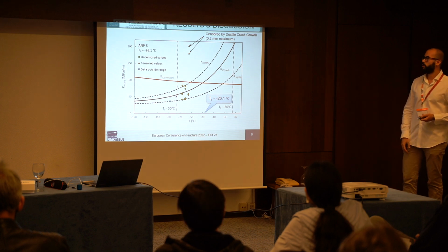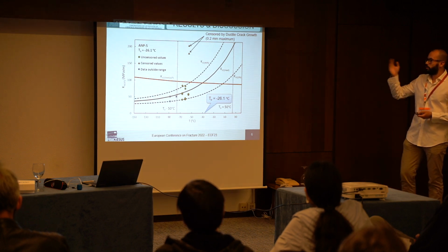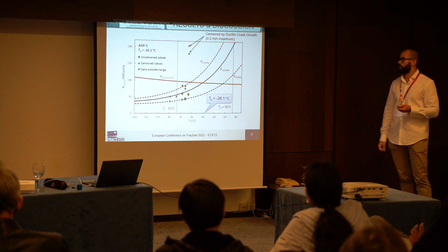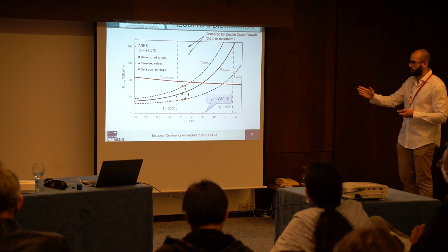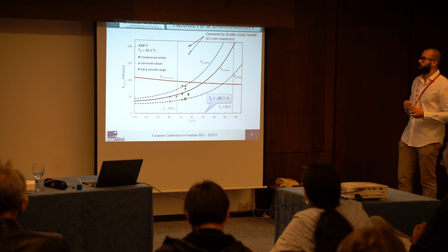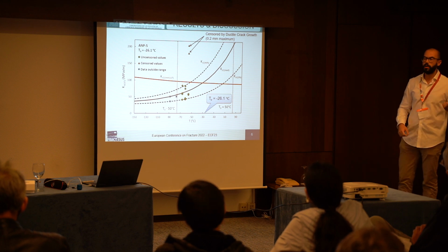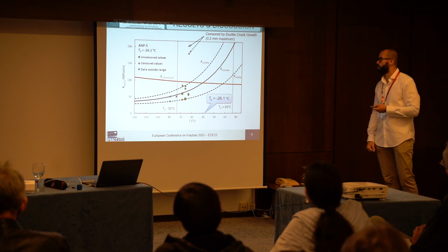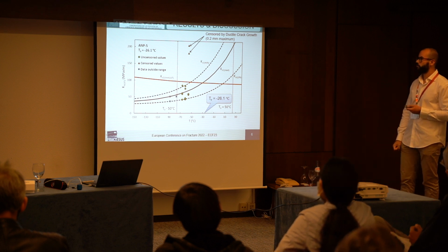Here you have the results. The T0 was -26.1 degrees. Also, we have included two common tolerance bounds, the 95% and the 5%.